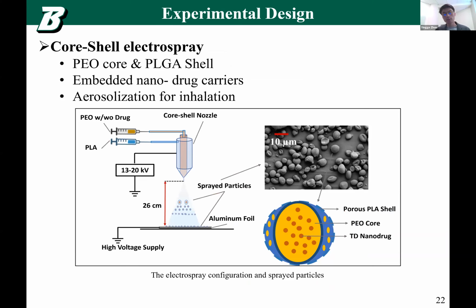So this is our setup. We used electrospray. The difference between electrospray and electrospinning is that electrospinning produces fibers. Electrospray produces particles. If you lower the concentration of the polymeric solution, then the fibers will be broken into particles. So we also got a core-shell structure in the electrospray. And then in the core, we incorporate their drug. Their drug is a nanocarrier drug. They call it TD nano drug.